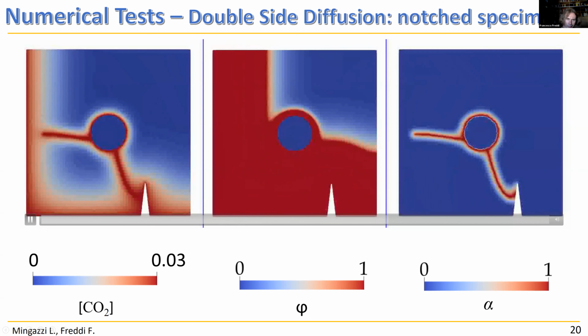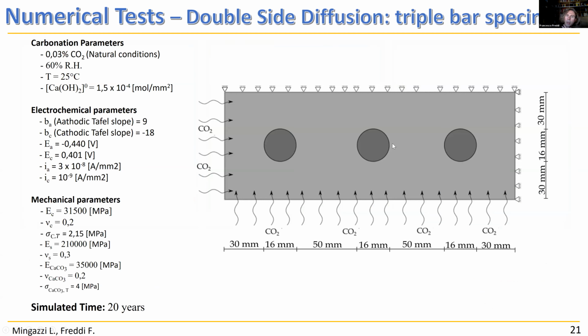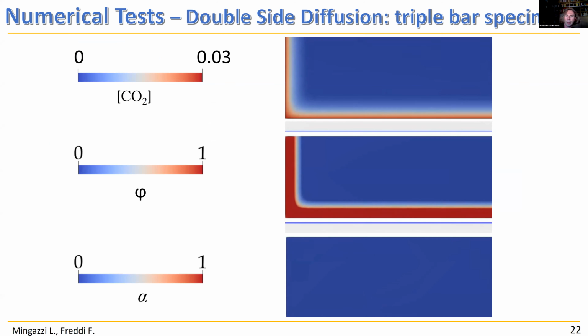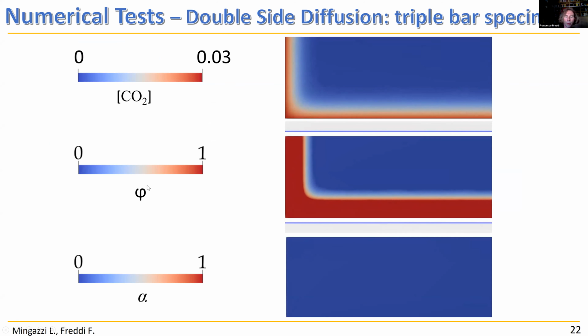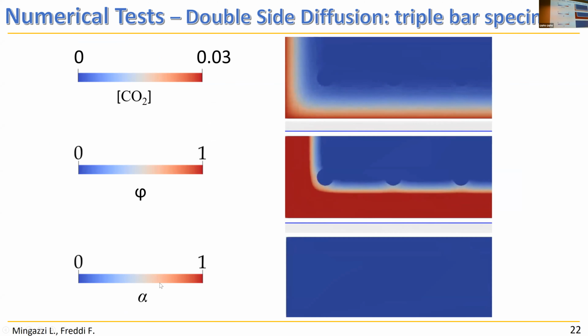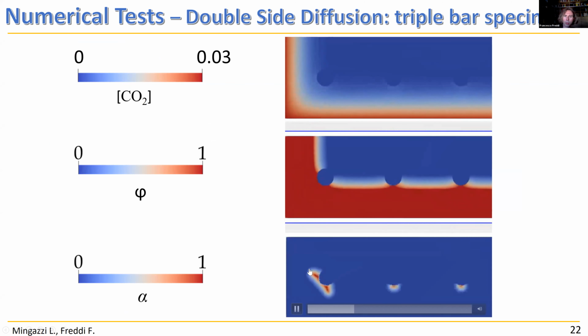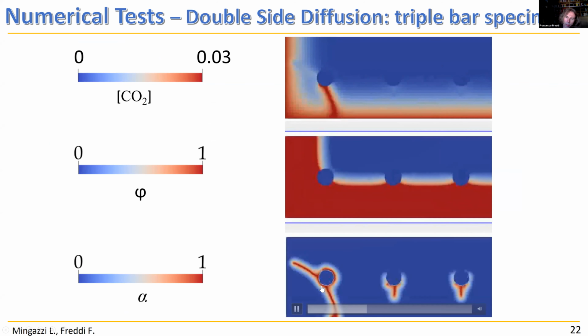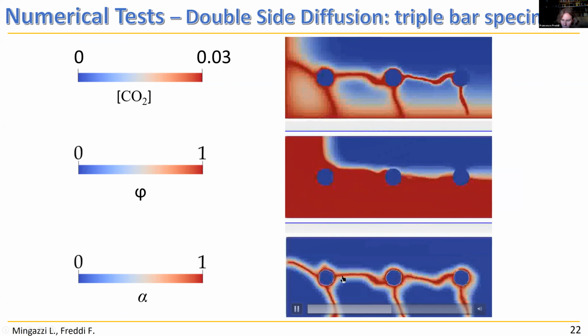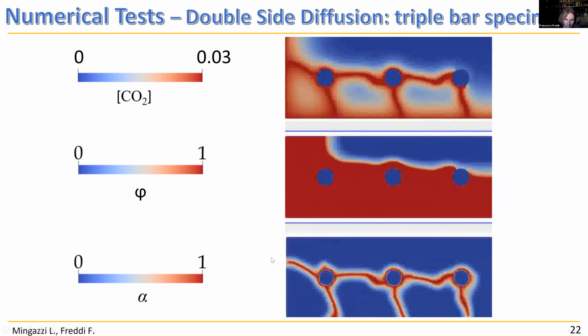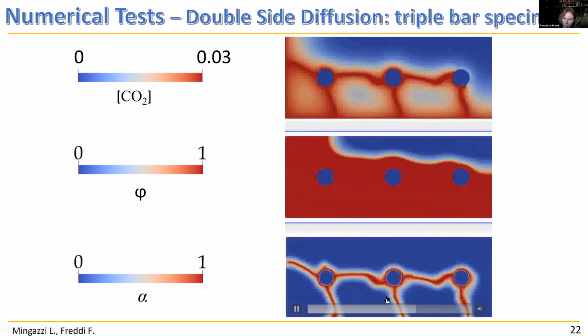In the last example, I'm considering 3 bars within a concrete element, just to see if the crack pattern may be different. And the CO2 diffuses along these borders as before. And this is always the solution in terms of CO2, carbonation front, and cracks. You can see initiation starts at this bar that is near the corner. After a certain point, there are cracks that connect the bars, in some cases they interact, and there are some cover spalling and also a delamination of the cover.